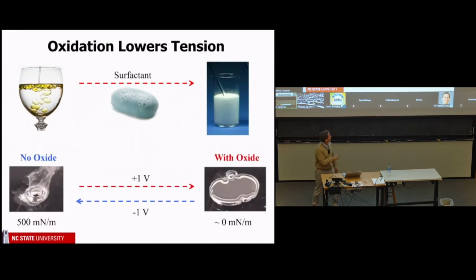In our case, we apply 1 volt and we apply our soap, which is the oxide. Negative 1 volt, it goes away and it beads up. It's easy to put soap into water, not so easy to get it to go away. Ours is completely reversible and we're getting huge changes in tension.